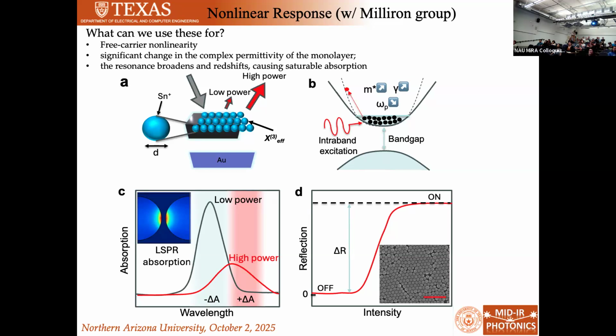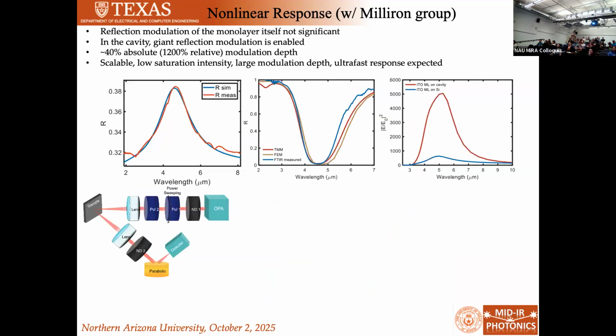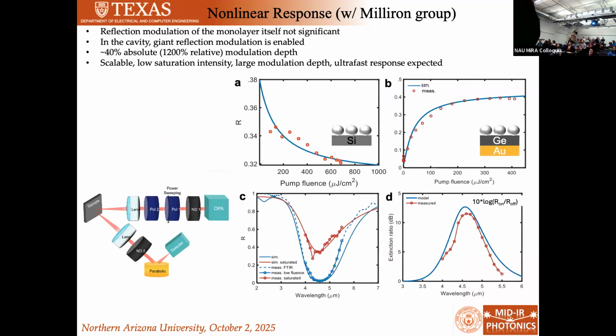So the idea was, if we apply a pulse of laser light, can we go from this zero reflection state to a state where we have high reflection, right? And the answer is, in fact, here we go. If we just put these nanocrystals on a silicon substrate, we see maybe a 2% change in reflectivity. But when we put it on our cavity structure, we basically go from zero reflectivity up to 40% reflectivity. It's an enormous change in reflectivity. And it has some real implications for optical switching and mode locked lasers, right?